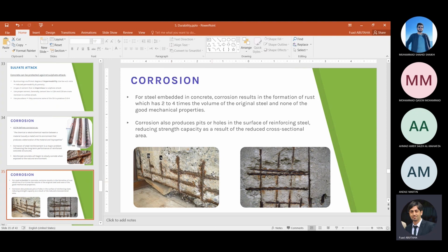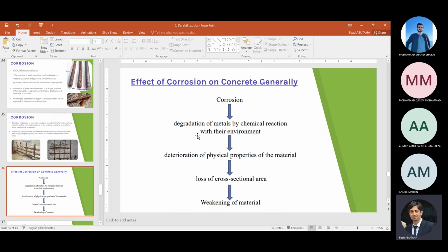As a result, there is rust, and the volume of the outcome of this reaction is higher than the original volume of the material that is reacting together. So the volume inside starts to increase, then it will try to push. Something inside the concrete is expanding and increasing, so it will push the material to the surface, and it will end up with something like this, spalling. We call it spalling, and all of this contributes to the concrete failure.